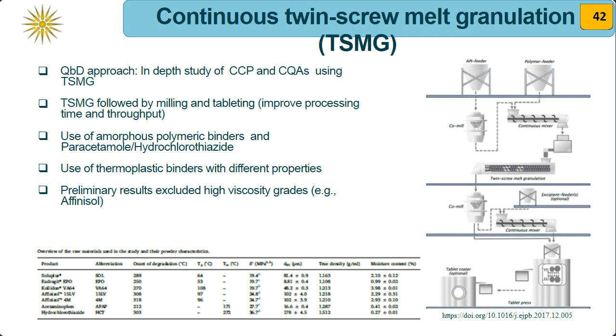One of them was Affinisol, which is hydroxypropyl methyl cellulose. In the bottom table, we can see the different properties of the binders that were used during the study, and it includes the glass transition, the melting point of the binders, the solubility parameters, the particle size distribution, and also the true density and the moisture content of these materials.